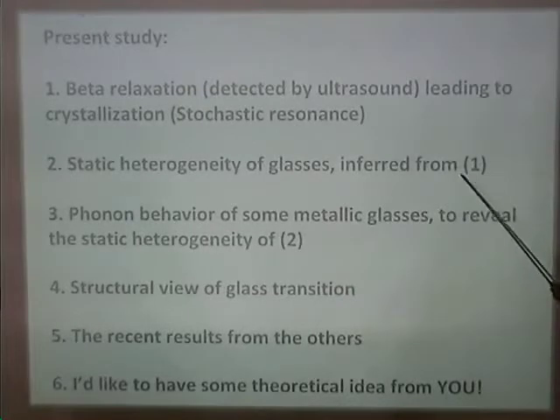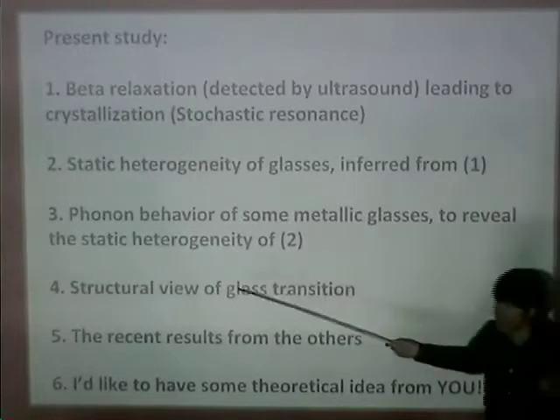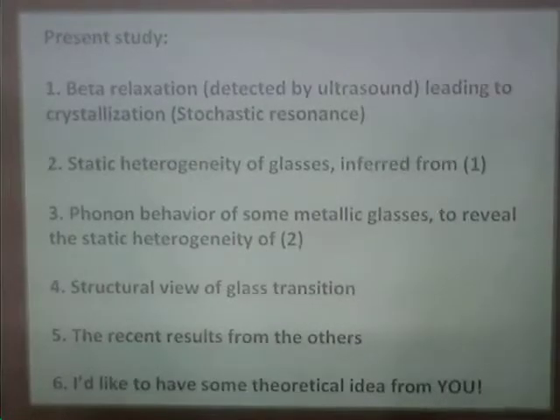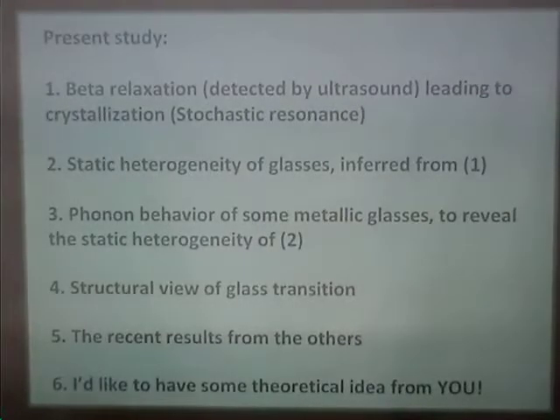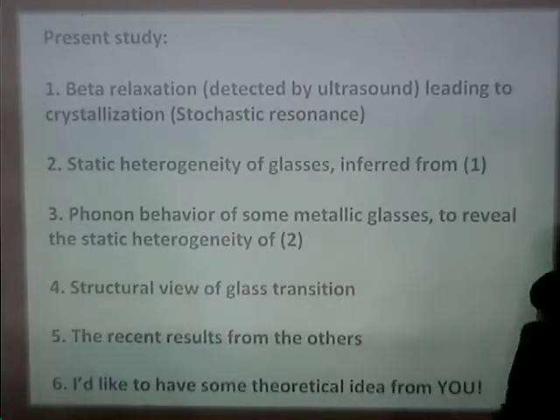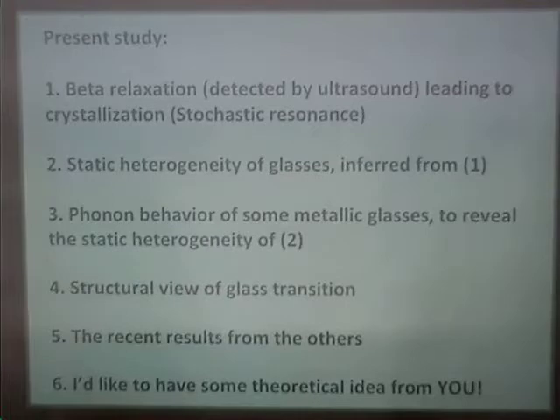reveal and validate this model, we have employed two methods. One is ultrasonic sound velocity measurement, and the other is inelastic X-ray scattering measurement. We have studied the phonon behavior of metallic glasses, and I would like to address a structural view of the glass transition. We also introduce some recent results from others. And what I want most from you is some theoretical ideas. So please give me some.